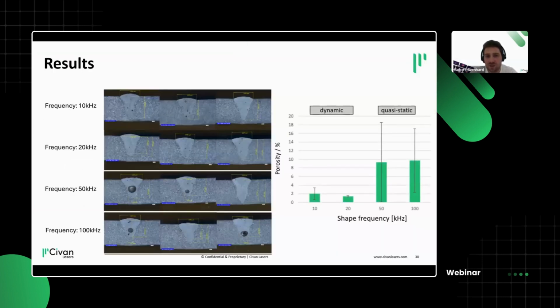And something very interesting to show, I think, is that there are sweet spots in terms of dynamic shape frequencies. Now it's more on the scientific side, but I really find this fascinating personally, because you can see a trend where we are here in the dynamic regime, and then we go to the quasi-static regime, and quasi-statically, this process doesn't work. We have a lot of porosity. There are problems with hydrogen exploding, kind of.